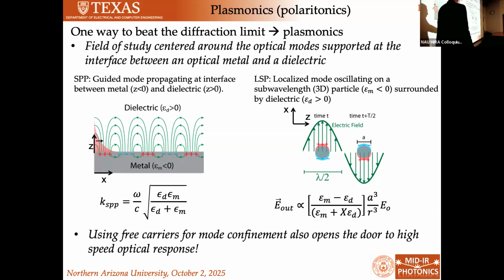This is the dispersion relation for a surface plasmon. It gives the momentum of this mode as a function of frequency and the dielectric of your material, right? And by the way, this is the permittivity of your dielectric, and this is the permittivity of your metal. When the permittivity of your metal and the permittivity of your dielectric are equal but of opposite sign, then this denominator goes to 0, and your wave vector effectively goes to infinity. So what does that mean? Well, the wave vector is essentially the inverse of your wavelength. So now the wavelength of your surface plasmon polariton has gone down to 0.